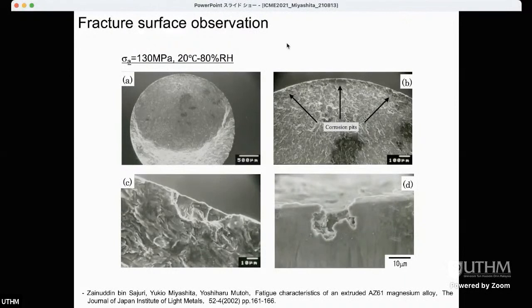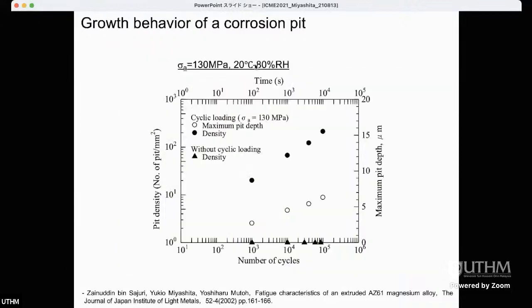Yes, like this. This is an example of fracture surface observation. This specimen was broken at a high humidity condition. As you can see from this figure, we could observe the corrosion pits at the fracture surface, especially from the fracture origin. So fatigue crack started from this kind of corrosion pit. And this picture shows the surface of the specimen. You can clearly observe this kind of corrosion pit after fatigue strength test at high humidity.